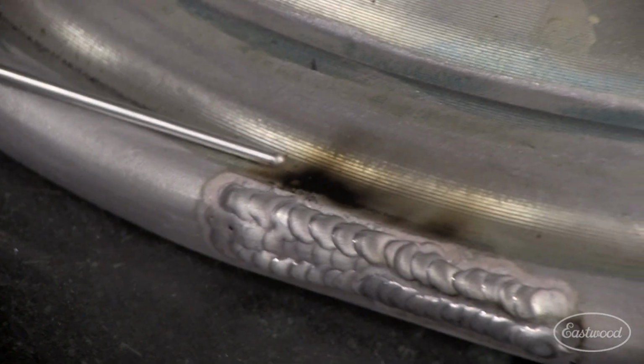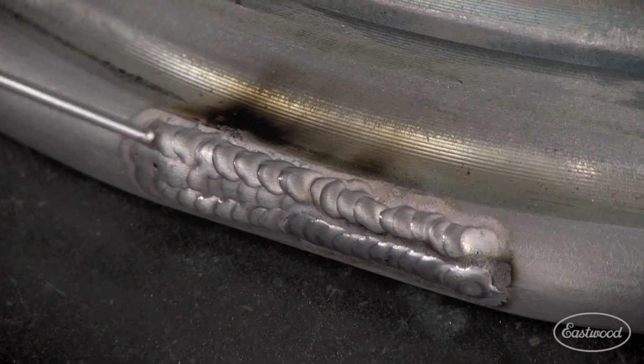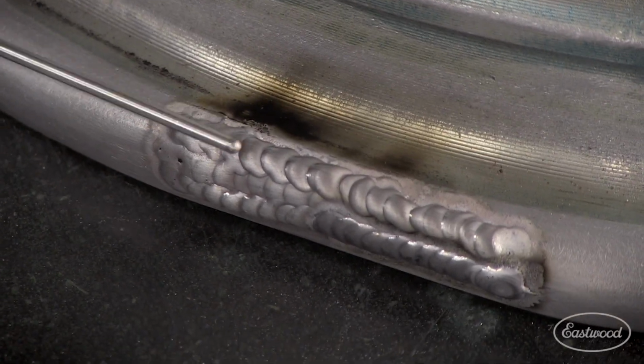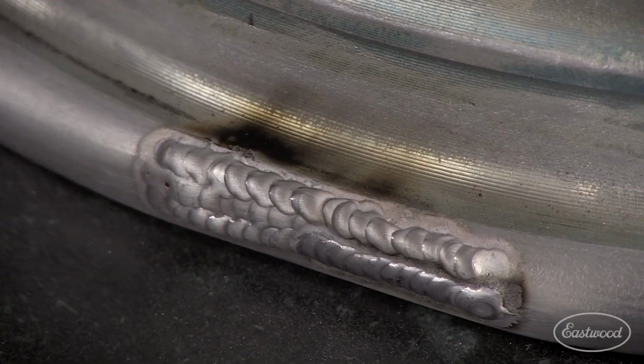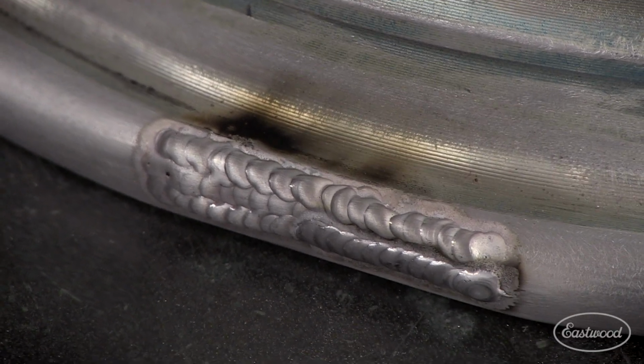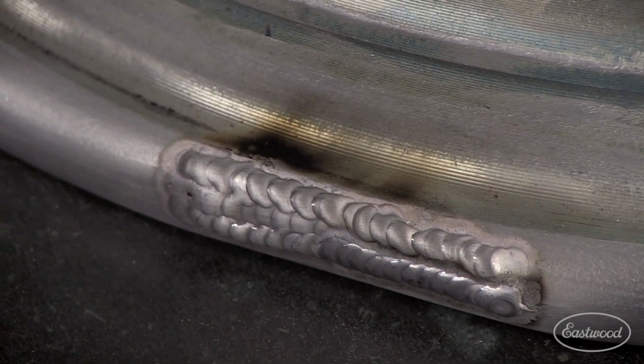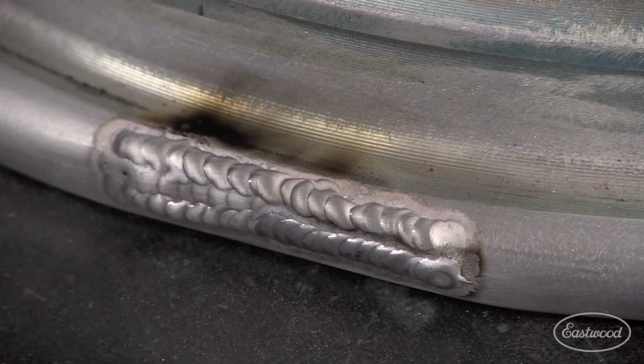You start seeing that black soot around it. You start seeing like salt and pepper kind of in your welds. That means you didn't clean it well enough. You probably got a dirty metal where you contaminated your tungsten, and that's what's causing that issue there. So that's a common thing that you can do.